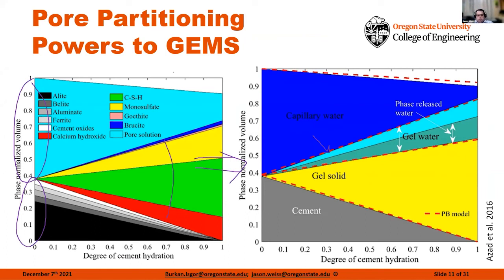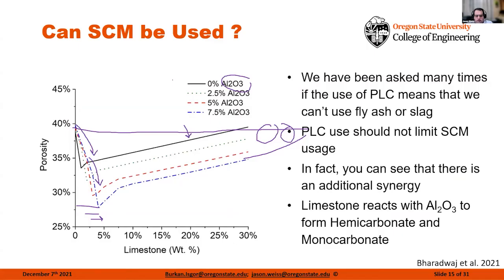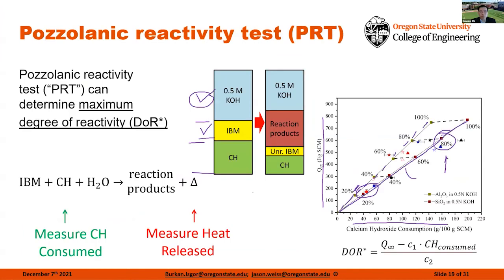If you would have asked this question 6 or 7 years ago, the entire field was assuming that when you put the SCMs in, they were 100% reactive, which is about 70% the wrong answer, right? These materials in general, a fly ash is generally about 20 to 40% reactive. And this is really where we bring in this pozzolanic reactivity test, because all of a sudden now what we can do is say, you have a particular SCM, maybe it's this SCM that's shown down here in red. This has a reactivity of 25%. The other 75% is inert material that's never going to react. So we can actually build that into the system and get much, much more accurate measurements by doing this, because we're actually considering those reactivities.